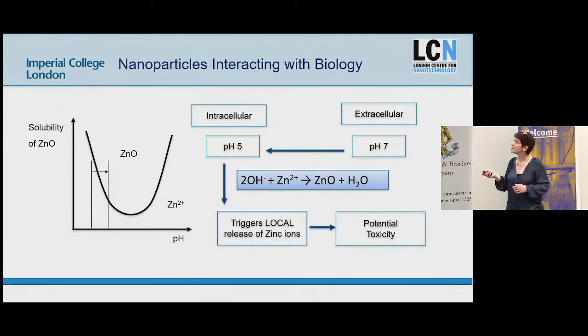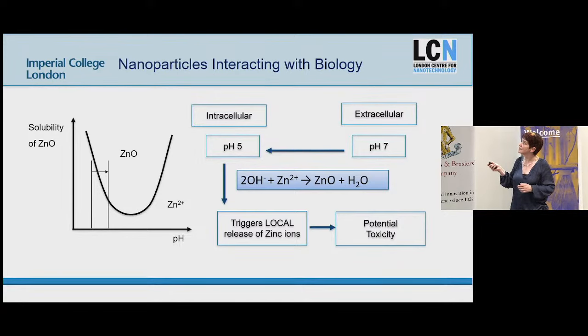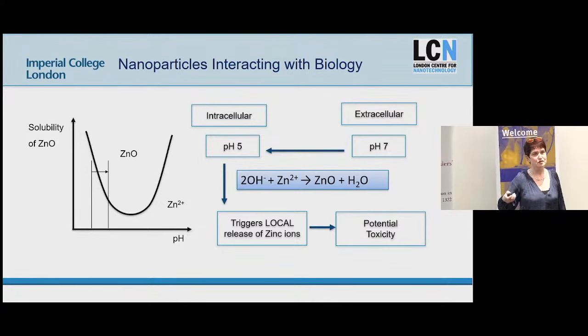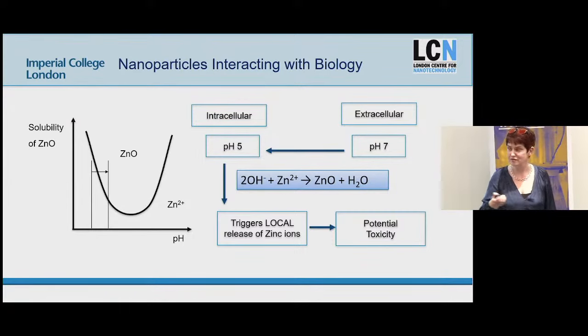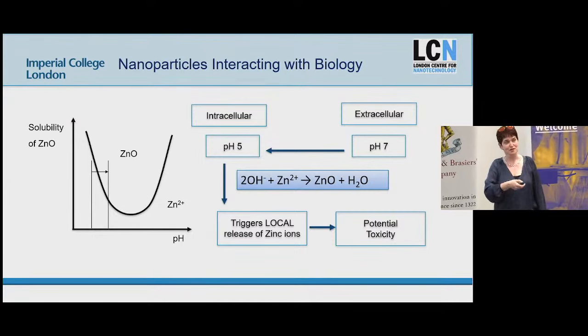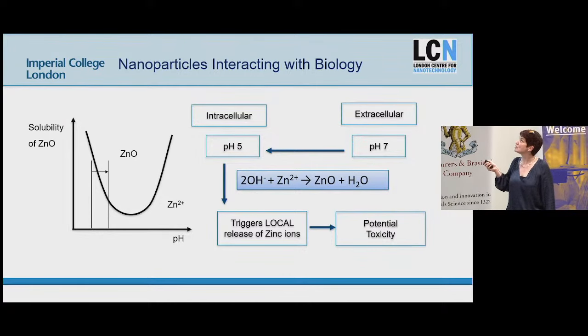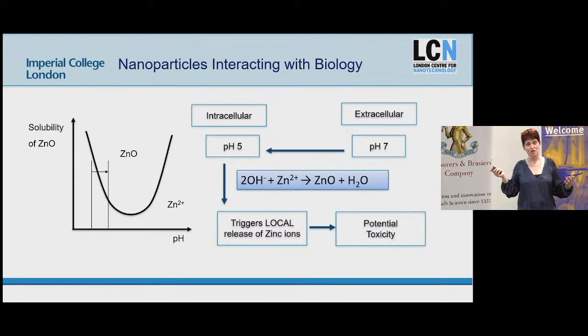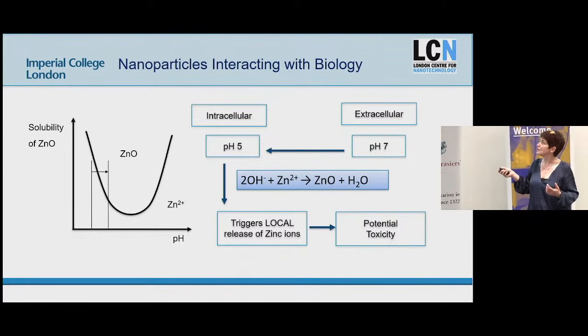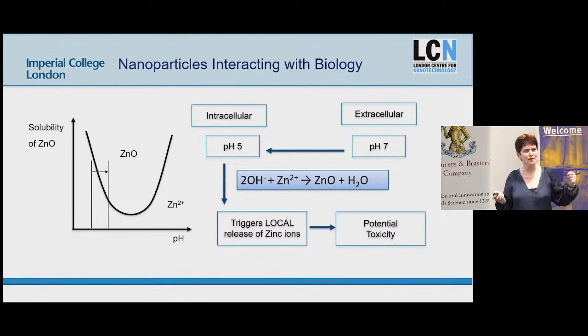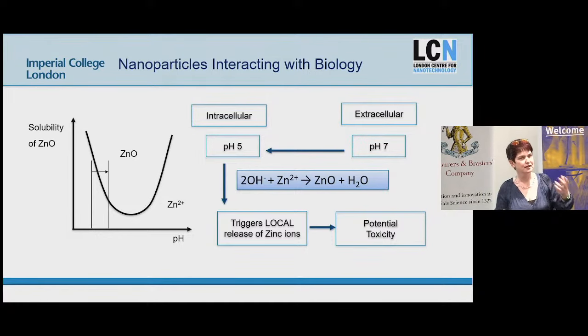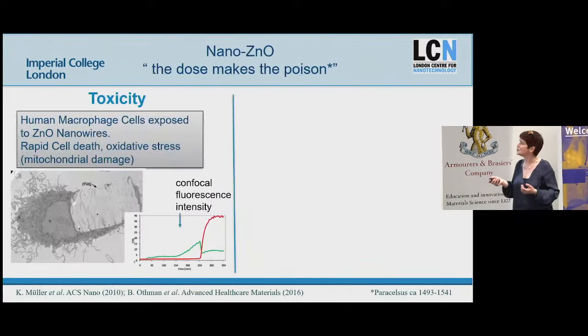Okay. So I just talked about going in this direction from liquid or solute to solid. Now, it turns out there's a really interesting system, and it's biological, where you have lots of scenarios where you go from pH 7 to about 5. So 5 to 7 takes you to deposition, 7 to 5 takes you to solution. In biological systems, the extracellular pH is normally about 7, intracellular is about 5. You're going to release zinc oxide. And I just told you that these particles were very small, so they can get across cell membranes, so they can go from extracellular to intracellular, and then they might well dissolve. And it turns out they do.